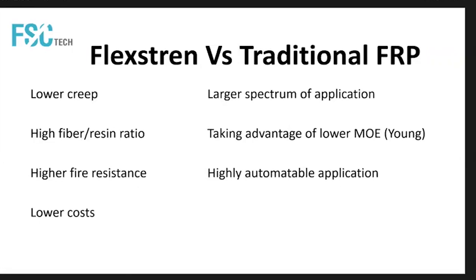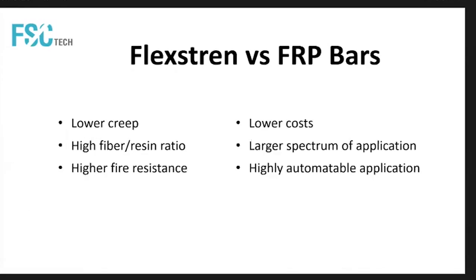You are taking advantage of the lower Young's modulus, basically because you are stretching it. So a lower modulus means less loss of pre-stressing or post-compression. We name that process post-compressing, because if you have a little bit of shrinkage and a high modulus, you get quite a high loss. But if you are using basalt, you are looking at about 70 to 75 gigapascal modulus, versus steel, that is 200 to 210. It's quite a bit less, so you have almost one third of the loss of pre-stressing. And all those processes can be highly automated. It's another advantage.